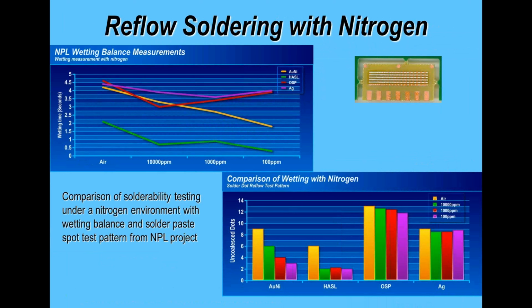not for all finishes. And if you look at the improvement between air reflow and nitrogen at 10,000 ppm, you're seeing an improvement. So after 1,000 ppm, you're not necessarily seeing a significant improvement when you then compare the cost of running your process. So you have to look at the actual levels of nitrogen you're using, the performance, and also the finishes you're using.